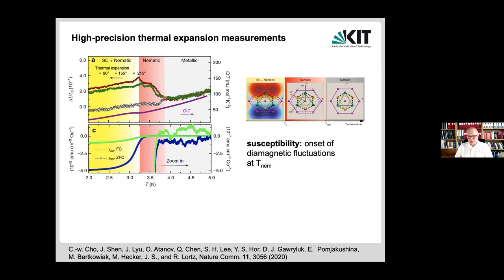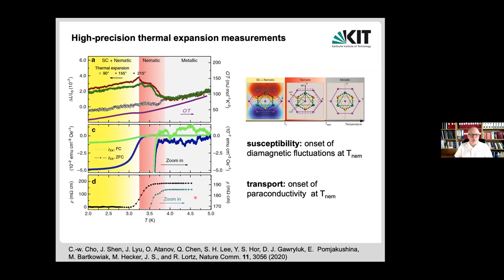taking place. And another measurement more recently was to look at paraconductivity. So again, this is the resistivity. This is the superconducting transition. And here we see the onset of superconducting fluctuations impacting the resistivity at the temperature where you also break the rotational symmetry. So there is therefore quite some evidence that indeed we have a composite order building where fluctuations of the superconducting order parameter condense and superconducting fluctuations are being enhanced without actually causing superconducting symmetry breaking.